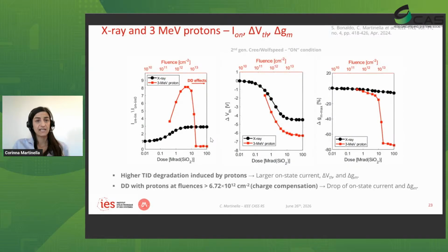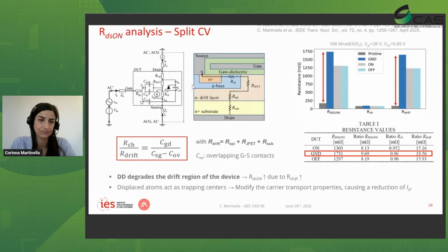If we compare X-rays and 3 MeV protons, again looking at the same figures of merit, we can see how the total ionizing dose induced by the protons was higher. So you can see the red line here, the degradation induced by the proton is higher with respect to the photons that we're using. And then you see this sudden drop in the currents, which you don't observe with the photons, indeed due to the displacement damage and the charge compensation induced in the device.